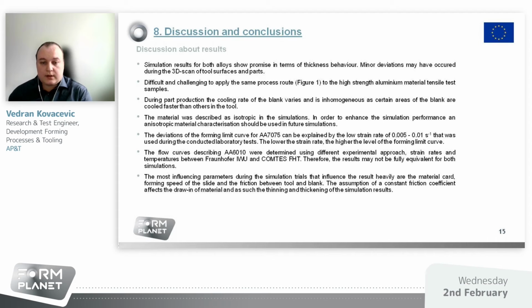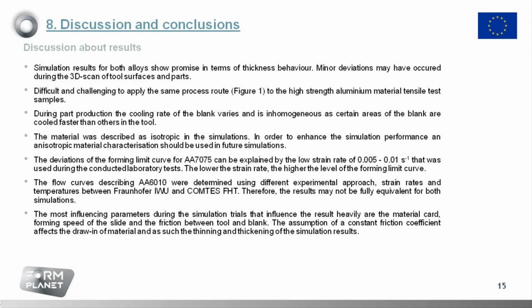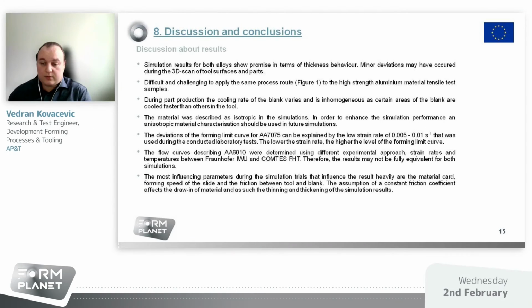To sum up, the simulation results for both aluminum alloys show promise in terms of thickness behavior compared to the formed parts. However, it is challenging to apply the same process route, which is usually present in an industrialized hot forming process, to the hot tensile tests conducted by Fraunhofer and COMTES FHT. Further, it must be highlighted that the flow curves describing AA6010 were determined using different experimental approaches, strain rates and temperatures between Fraunhofer and COMTES FHT. Therefore, the results may not be fully equivalent for both simulations.